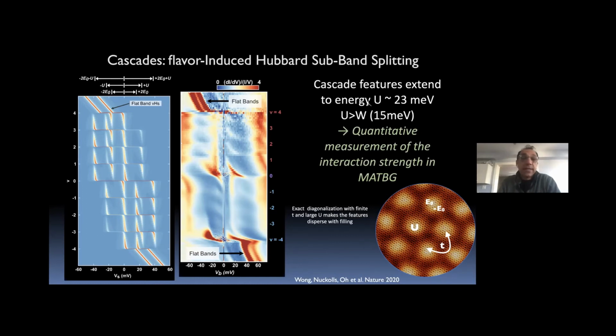Now, I should add that in the samples that we make, the gate is actually quite far compared to the samples you just heard about from Dimitri, where he tunes the distance between them. So that's actually an interesting experiment to do. He also told you about changing the twist angle. And if we change the twist angle from the magic angle, all these correlated features that I told you about disappear. And if you have a question about that, I can show you those results at the end.